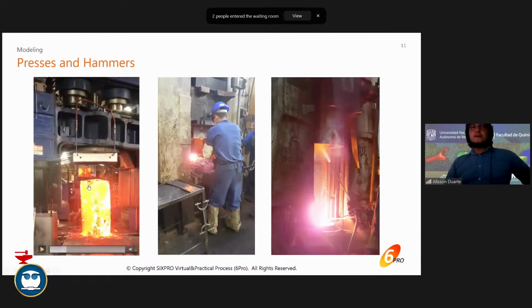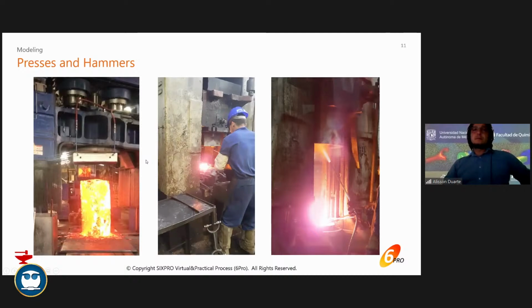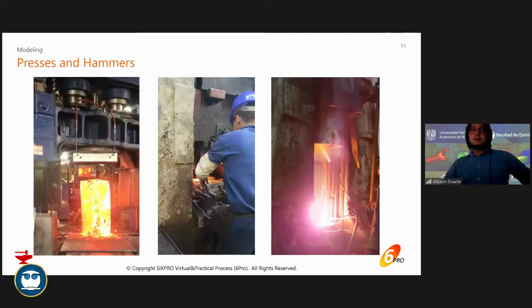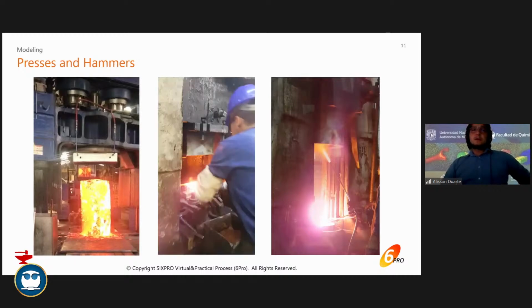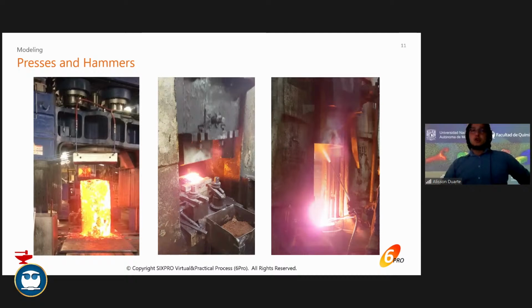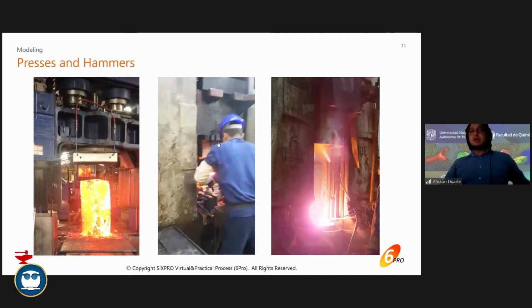I think it's enough. So we're going to see that it goes upsetting this big bar slowly. Then you have this mechanical, this is a friction press. So it's interesting. Here you have two blows with the same die. It's faster than this process here, this hydraulic press on the left, and in the center you have this friction press, and you do two blows.